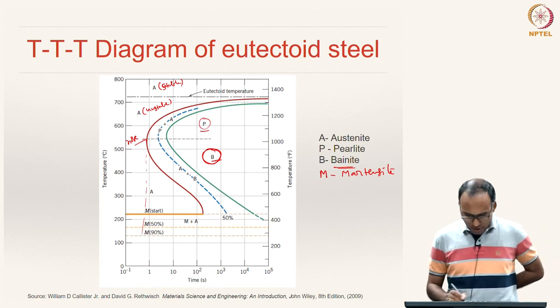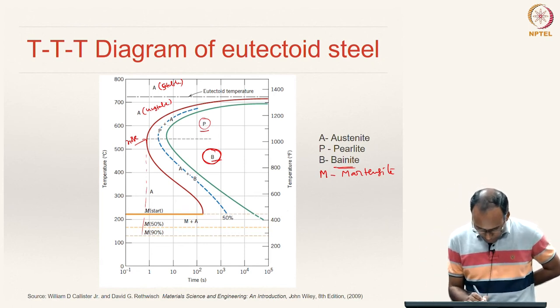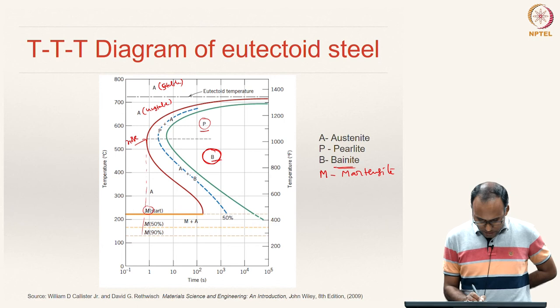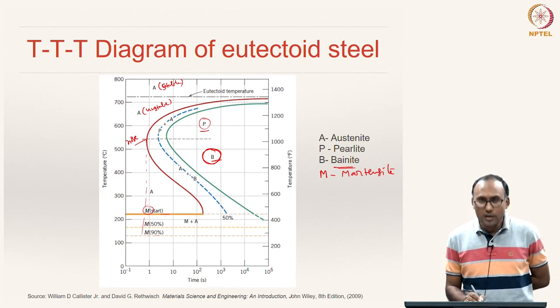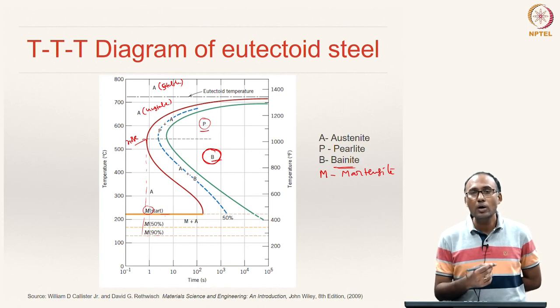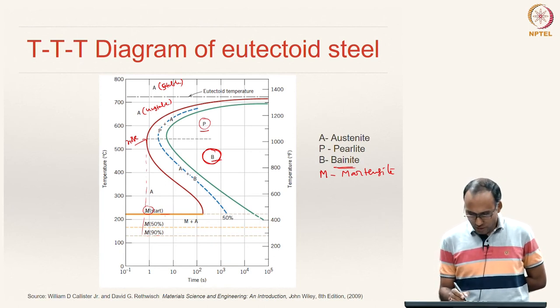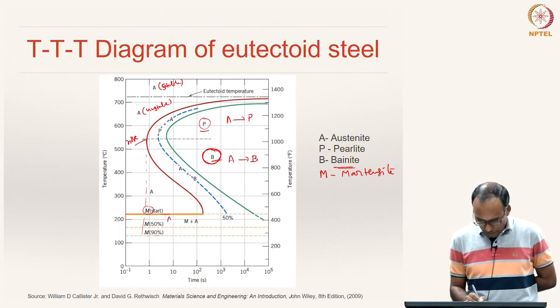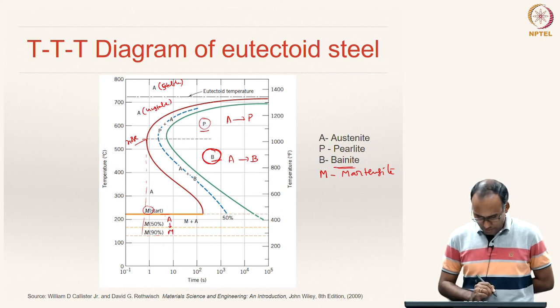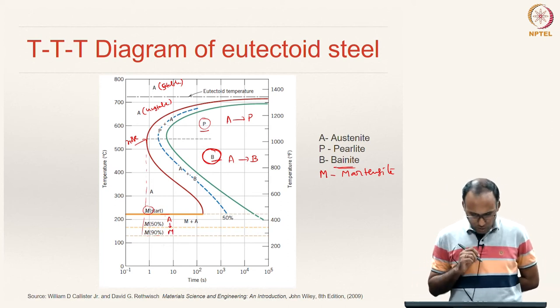At very low temperatures, martensite forms — shown by orange lines representing the martensite start line and martensite 50% line, with a martensite 90% line further out. So in the upper region austenite transforms to pearlite, below the nose to bainite, and at very low temperatures austenite transforms directly to martensite.